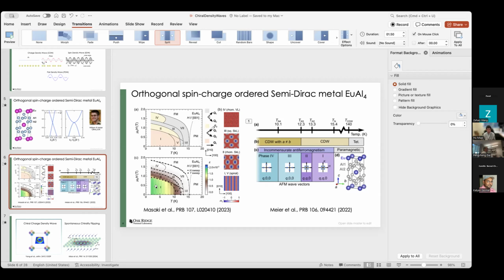So we have an experiment trying to test if we can use resonant X-ray scattering to directly characterize the chirality of a CDW. So far, all the evidence is indirect. We don't have the magnetic X-ray scattering type of measurement to directly say it must be a chiral CDW. All the measurements are based on symmetry arguments, but we are doing soft X-ray resonant elastic X-ray scattering, with the hope that we can directly determine the chirality of the CDW. Then we can trace more carefully how the chiral spin density wave affects the chiral CDW. Maybe the chiral CDW forms the basis for the chiral SDW.